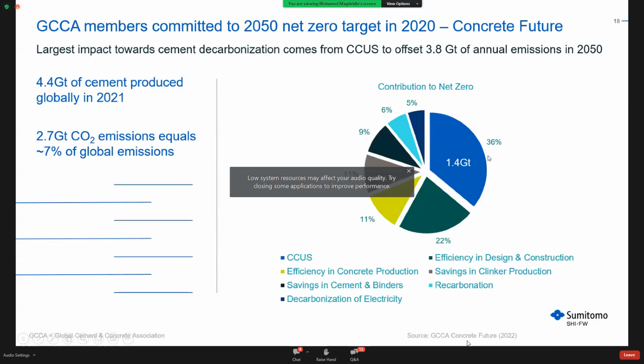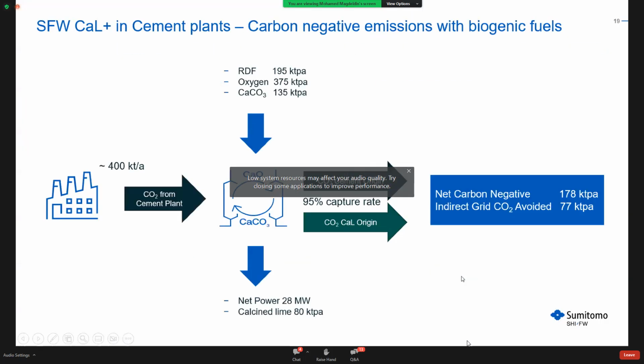But if we go to the cement plant case, and this is a result of a feasibility study, as I mentioned, we looked at capturing 400,000 tons per annum of CO2 from an existing stack. We looked at utilizing RDF or waste-derived fuels in our calcium looping system, and we captured over 95% of the CO2 that's generated in the plant while producing net power of 28 megawatts for the plant and additional calcined lime of around 80,000 tons per annum.